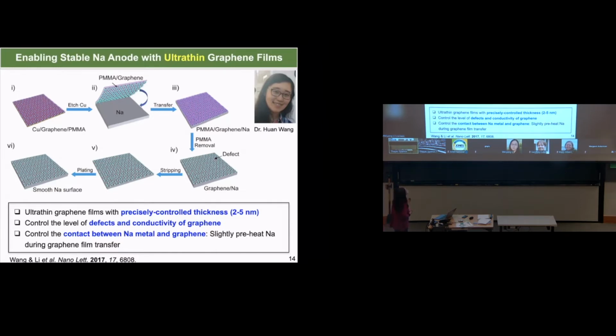At that time, we were trying to think of how we could take advantage of this expertise to synthesize a very thin layer of graphene material and coat the graphene on the surface of sodium metal, to use this graphene material as an artificial solid electrolyte interface layer. Dr. Huan Wang successfully synthesized graphene with the thickness precisely controlled around 2 to 5 nanometers, and we are able to control the level of defects and the conductivity of graphene by controlling the synthesis temperature.